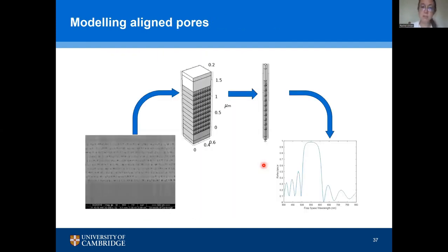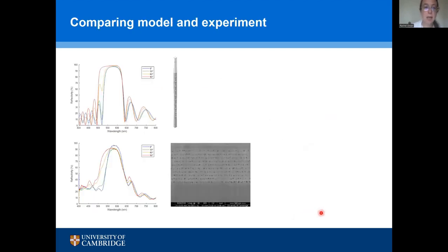We just produced some models of this using COMSOL, finite element type modeling. So we've modeled this as being cylindrical pores in layers running through the material. And we can use that structure and model our expected reflectivity curve against wavelength. And then we can think about the polarization of the reflectivity. So here is our model data, assuming these aligned cylindrical pores. And we can see that as we change the polarization of the incoming light, what we actually see is we're losing part of the stop band as we rotate the polarization, and we're narrowing down the stop band.